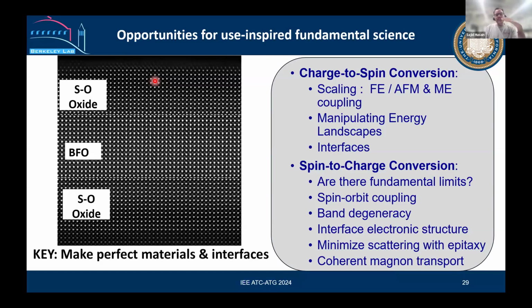So this is limited by the set of instruments, electronics. We have reported this up to 100 picoseconds. So you can switch this polar state up to down in 100 picoseconds. That's pretty fast. That's a limit of the instruments. And of course, the device size, the RC constant, is also limited by the device size. If you reduce your device size a lot, the resistance and capacitance product, you can switch faster. So 100 picosecond is the limit that we have seen in our device size of like a micron size.